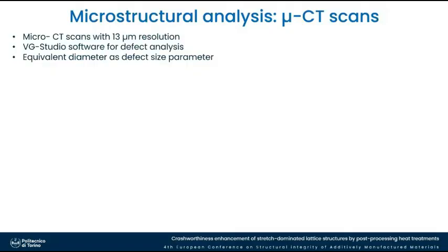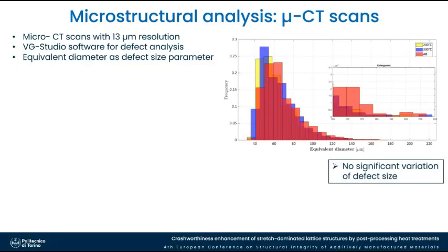So we started from the micro-CT scans that we performed. For us, the equivalent diameter was the defect size parameter. And the first thing that we observed was that there was no significant variation of the defect size with the three heat treatments, as you can see in this figure.